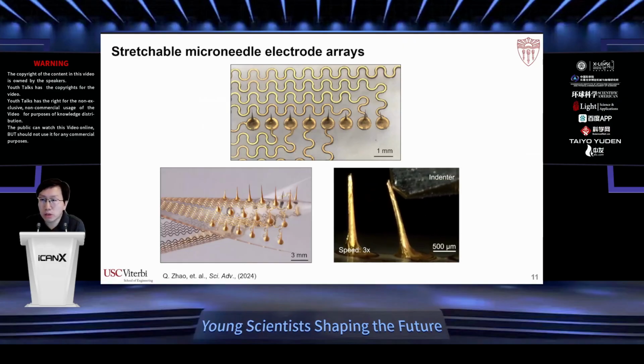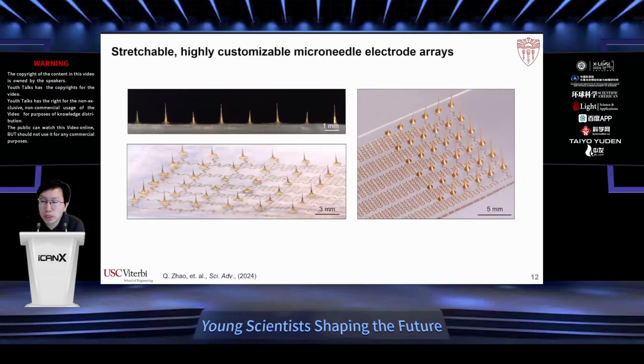And these microneedles and the serpentine interconnects are bonded to a highly stretchable EcoFlex substrate. Because of the covalent bonding, the adhesion is very strong, so the needles can deform without delamination. And more interestingly, because each microneedle geometry is determined by the laser micromachining process, we have complete control over the dimensions of individual needles, which is advantageous for targeting specific regions in tissue, for example, different depths.